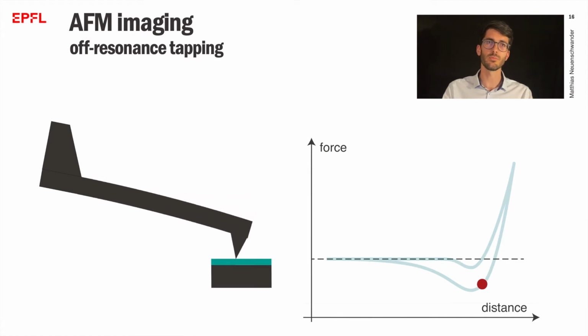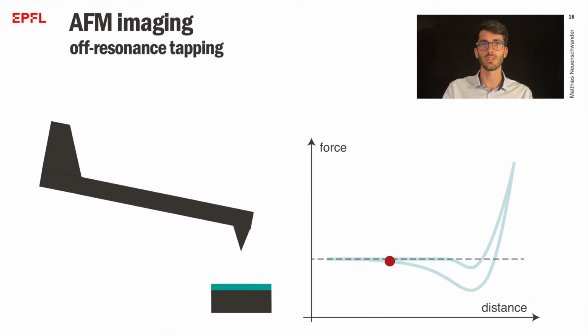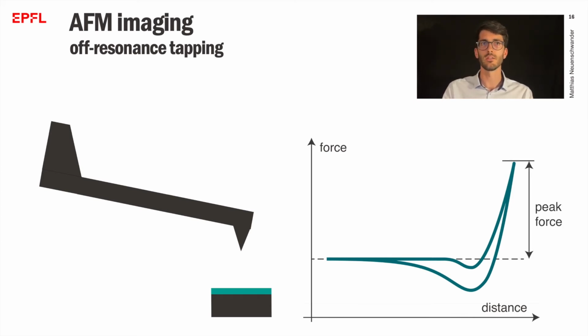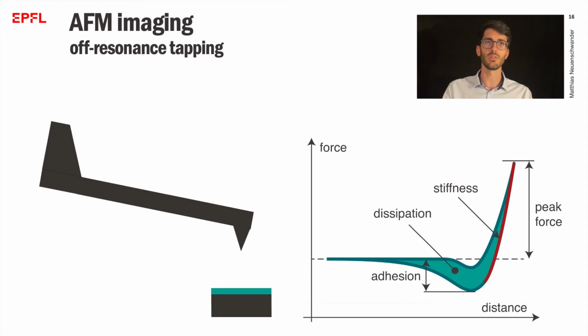The sample then moves back away, and adhesive forces retain the tip for a bit, until it snaps off and goes back to its initial position. This procedure allows us to obtain a few thousand force distance curves per second. Different parameters can be extracted from the curve, such as the peak force, the surface adhesion, the stiffness, and the energy dissipated during the cycle. These give valuable information about the mechanical properties of the sample.